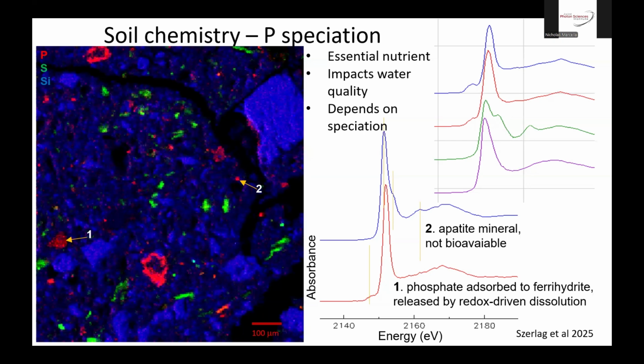And so the inset here actually shows some of the variations in phosphorus XANES for different phosphorus mineral species. And unlike the sulfur, where it's really spread out, these are pretty subtle. So you just see small shifts in the main peak position, or shoulder peaks, or pre-edge peaks, different features like that. So those are distinctive and still allow you to identify different phosphate species, but you have to look a little closer.